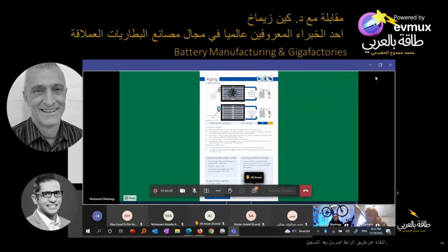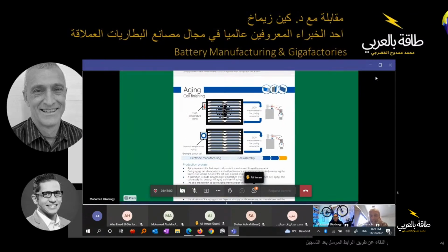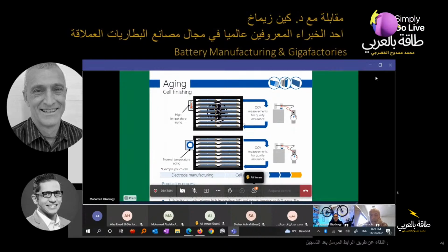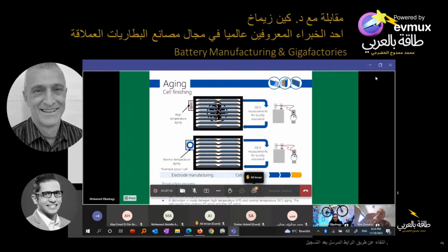Formation and aging is where you're doing your initial charge and discharge cycles, because it's not really a battery until you've charged it up and discharged it and charged it up a couple of times. And you let it sit to let more electrolyte soak in, and to let the SEI layer, the solid electrolyte interphase layer, form. It's basically a series of very slow charges and very slow discharges. And then sometimes you let it sit for 24, 48, 60 hours at high temperature, depending.